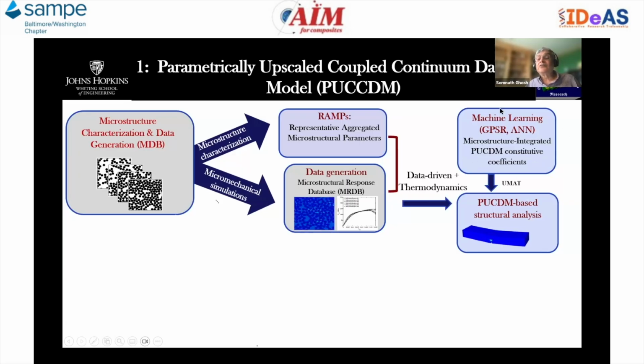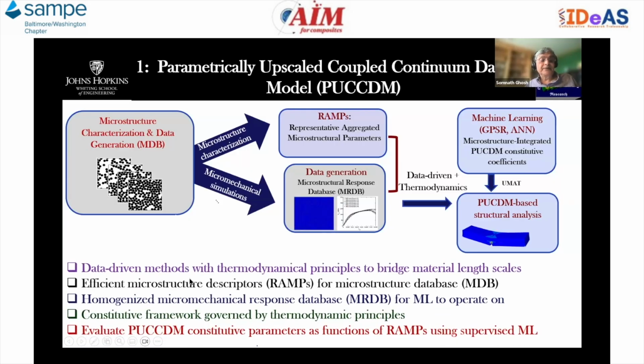The data-driven techniques will be necessary for my machine learning techniques to operate on that, to generate this PUCCDM constitutive coefficients. And then based on that, we will have the PUCCDM constitutive models that can be inserted in any structural analysis, to actually do the structural level analysis with direct linkages to the microstructure. So the advantages are the data-driven methods with thermodynamic principles are used to bridge material length scales, efficient microstructure descriptors in the form of ramps for the microstructure database, homogenized micromechanical response database for machine learning to operate on. The constitutive framework is governed by thermodynamic principles, and then we evaluate the PUCCDM constitutive parameters as function of ramps using supervised machine learning techniques.